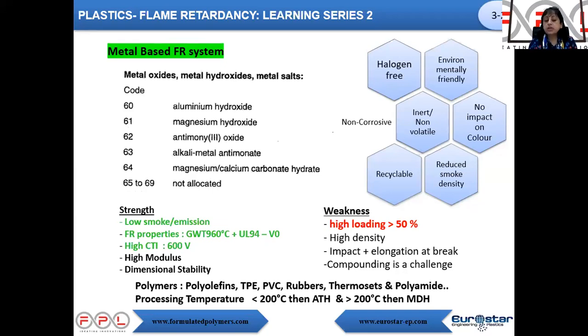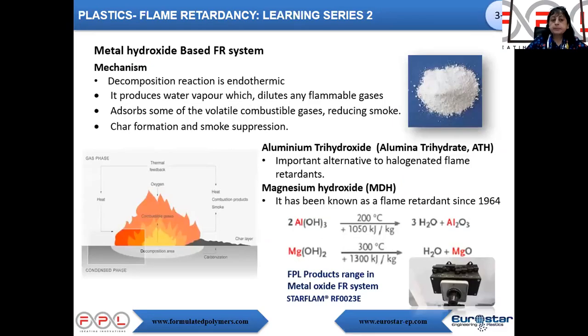The major polymers where metal-based FR systems are used are polyolefins, thermoplastic elastomers, vinyl chlorides, rubbers, thermosets, and also in polyamides. Now, if we look at the processing temperatures, in case the processing temperatures are less than 200 degrees centigrade, then we use aluminum trihydrate. And in case the processing temperature of the polymer is more than 200 degrees centigrade, then we use the magnesium hydroxide systems.